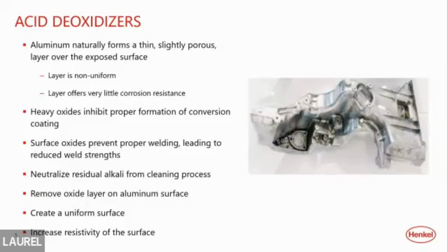So you've wasted time. It looks bad, and it could be a safety issue. So we have to remove that aluminum oxide layer. So we have to deoxidize it in some manner, either with an etch passivation, which is a process we have, or with an independent acid deoxidizer.